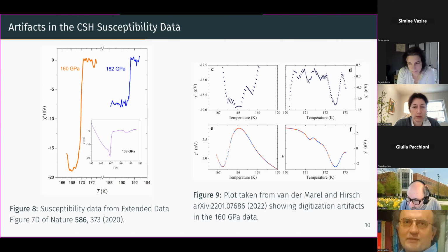that the authors, when they did a background subtraction, so let me explain the background subtraction briefly. At high pressure, this is a very, very tiny sample. And so this transition, particularly in low temperature measurements, could be riding on a large background. And so typically what you do is you measure at a nearby pressure where the TC is at a different temperature, and then you subtract the two measurements from each other, and you get rid of most of the background.